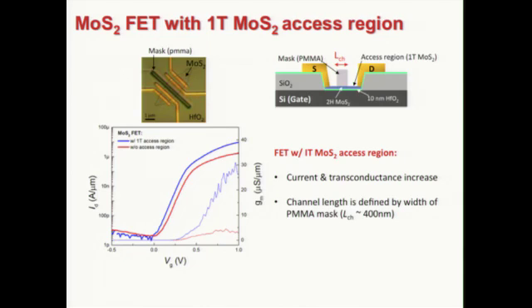Here in this work, we use PMMA mask. It's a long channel transistor, about 400 nanometer here. And then we apply the same phase transition, the chemical treatment. As you see, after the treatment, we still have a transistor, very large on-off ratio. But as you can see, the current and the transconductance have improved, so the junction is good. The series resistance is relatively small.